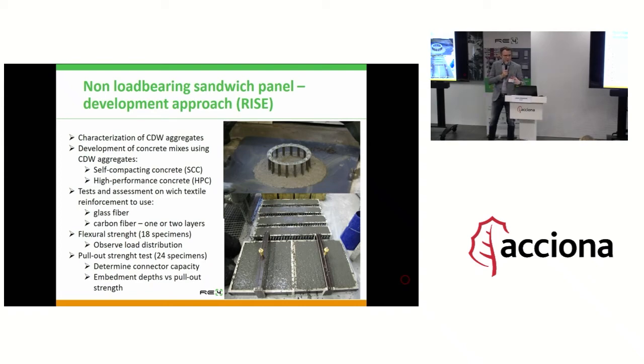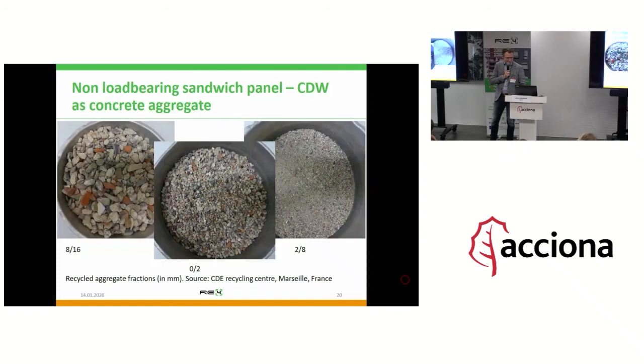And then we also, for the high performance concrete in the outer layer of this particular panel, made several tests at RISE to find the optimal textile reinforcement, because there is not only carbon fiber, you can also have, for example, glass fiber. But finally, we stuck with the one layer.